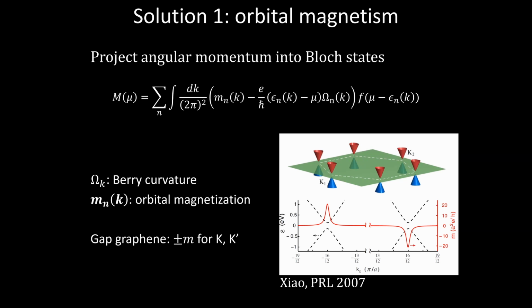The fact that you have these other flavors, these valleys, turns out to be very important, because if you can gap out these Dirac fermions, so if you can introduce some sort of perturbation which will gap them out, you get a lot of Berry curvature in that band. It's said that Dirac cones have incipient Berry curvature. Almost anything you do to them will give you a lot of Berry curvature. And if you get a lot of Berry curvature, you get a large orbital moment.